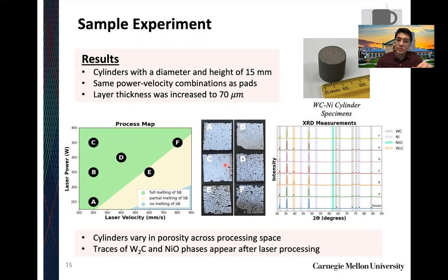In fact, those large pores are actually remains of a diamond polish, really. So they weren't there before. But B has very low porosity as well. A has some porosity as well, not as much as D, E, and F, which are clear lack of fusion, but still some left over.